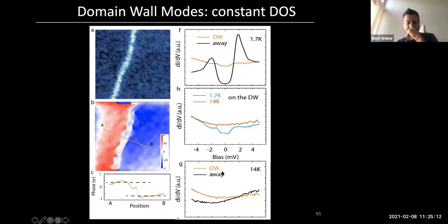Okay. Whereas, so it's not a 1D Dirac state in the normal state. Yeah, exactly. There's no special dispersion or anything like that in the normal state. What happens is in the superconducting state, in most places, you can actually see remnants of the coherence peak, which is actually really important, right? And then you see this finite density of states inside the superconducting gap.